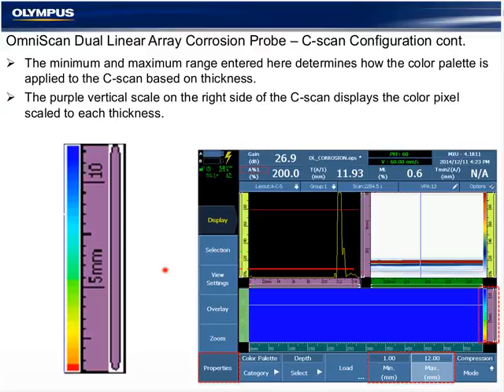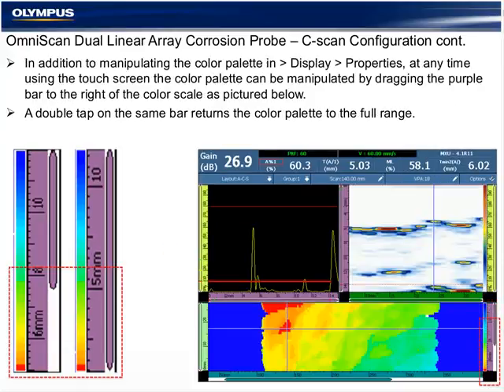After the UT and the gate are configured, the color palette is configured. Again, we have another range here that by default will be the same as our gate thickness range, and a combination of the gate length and start position, the thickness entered under the gate, and the color palette will determine the color of our C-scan. Color equals thickness, and it's going to help us in the C-scan analysis to find our low spots quickly.